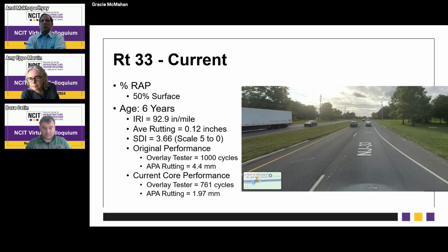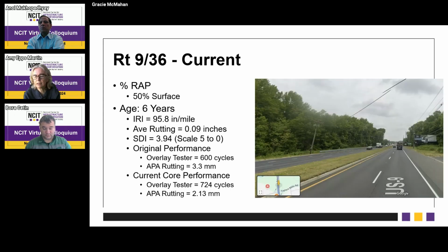Next slide, please. The next one has been out there about 6 years, and it is still showing very good cracking performance, very little or minimal rutting depths on the cores themselves. The SDI is still very high. The IRI is still just dropping near the threshold between good and acceptable, but still very good. Next slide, please. And the last one has also been out there about 6 years. You can see, again, very good cracking resistance, even after 6 years on the cores, minimal rutting, same story, high surface distress index, and good IRI.